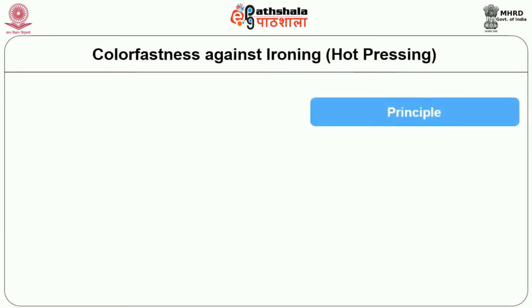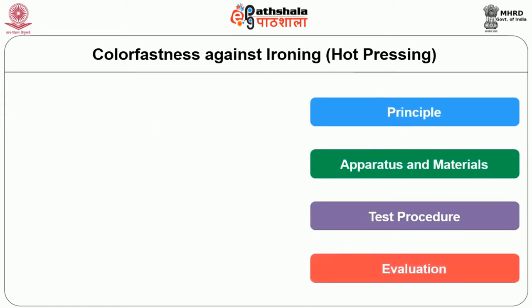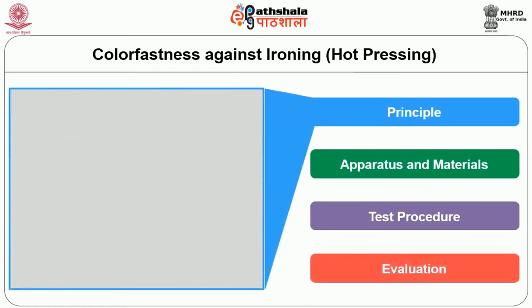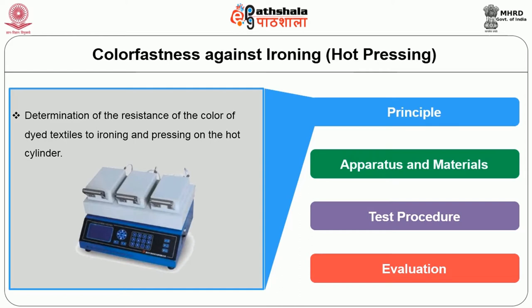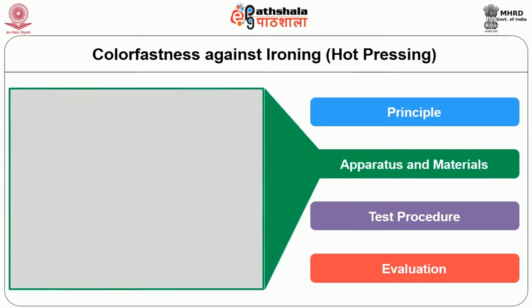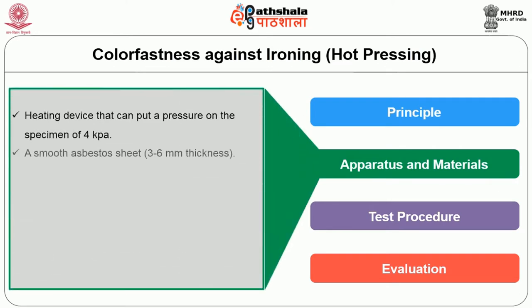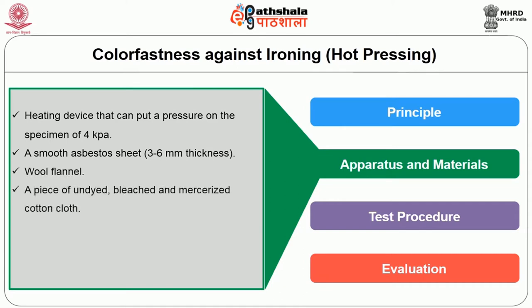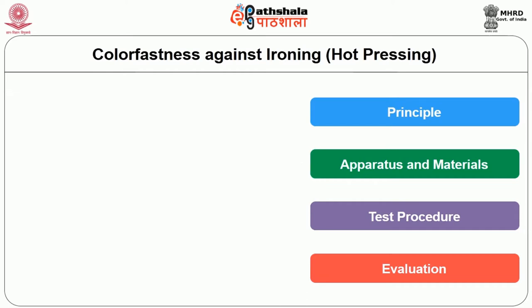Color fastness against ironing. Industry terminology is hot pressing. Principle used: determination of the resistance of the color of dyed textiles to ironing and pressing on a hot cylinder. Apparatus and materials required: heating device, smooth asbestos sheet of thickness 3 to 6 mm, wool flannel, undyed fabric, bleached fabric, even mercerized cotton fabric can also be used, grayscale, standard color matching cabinet, distilled water.